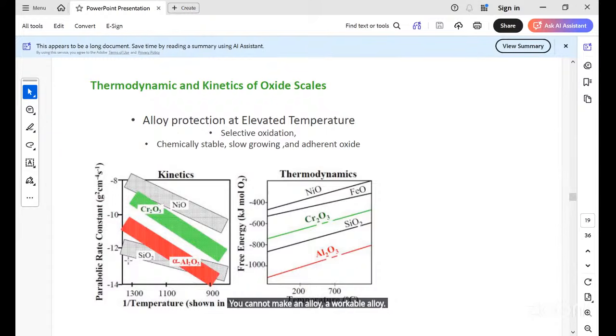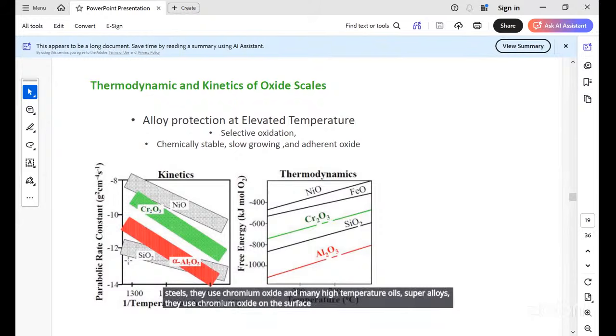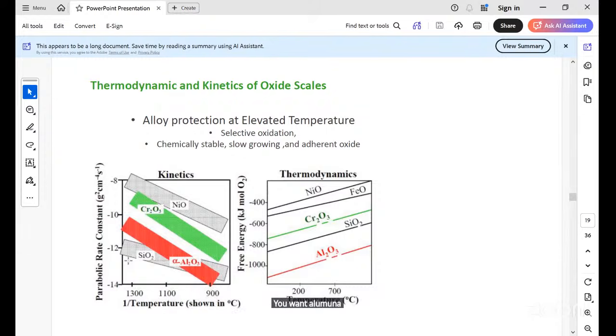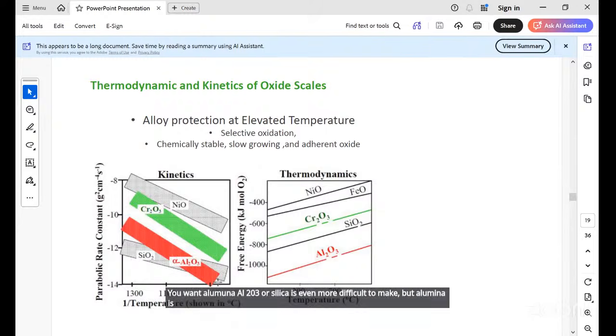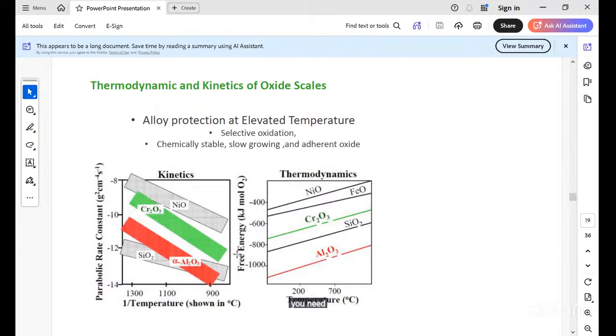So most alloys like stainless steels use chromium oxide, and many high temperature alloys, superalloys, use chromium oxide on the surface. But ideally, you want alumina, Al2O3, or silica. It's even more difficult to make. But alumina is a very practical system, and many systems use aluminum oxide on the surface, preferentially oxidized aluminum. You need only 6% to make an aluminum oxide at high temperature.